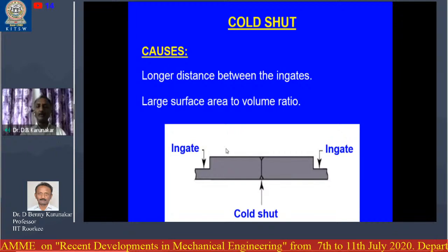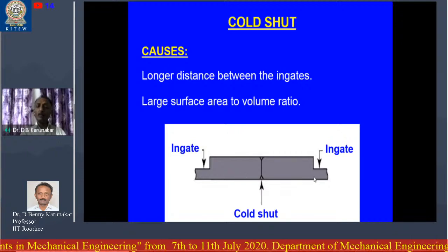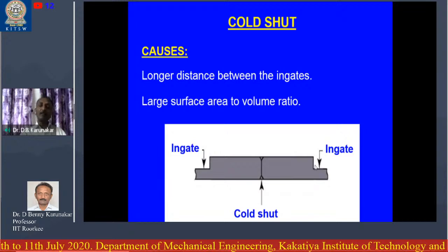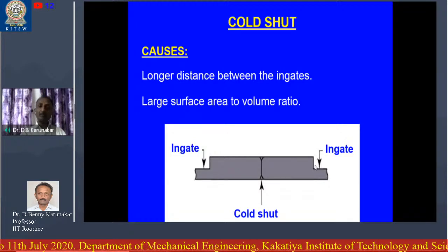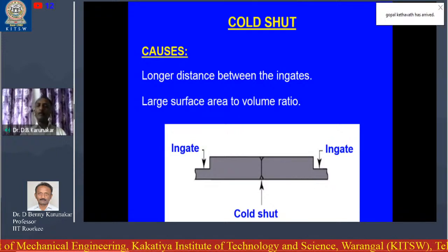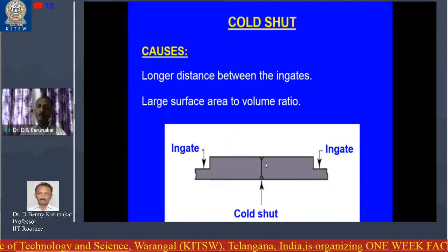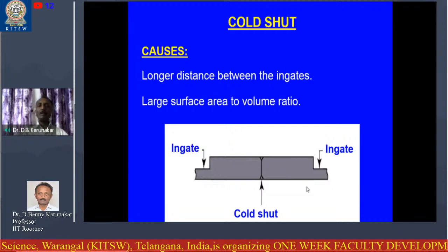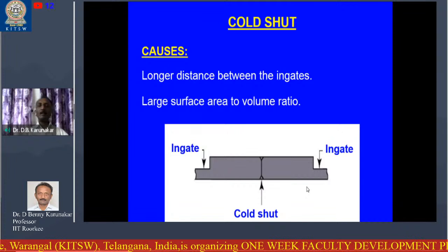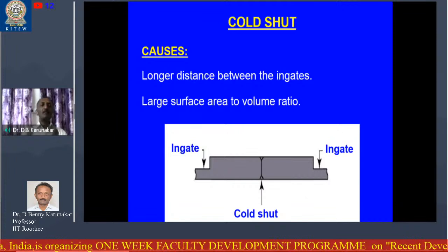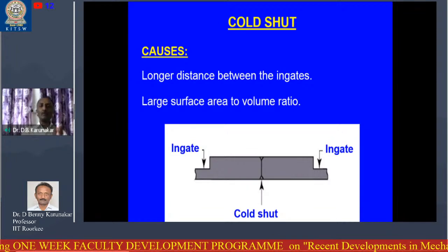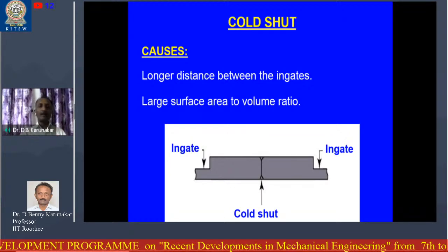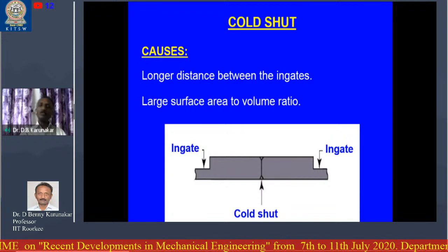Now, suppose the distance is too much, then what will happen? Initially, the molten metal had sufficient temperature. The temperature was high, so because of that, the fluidity was high. But as it was coming closer to inside and inside, it comes in contact with the molding surface. Then its temperature slowly comes down and comes down. By the time it comes to the center point, the temperature has almost come down, almost come to the melting temperature.